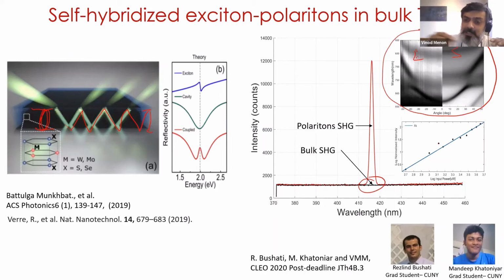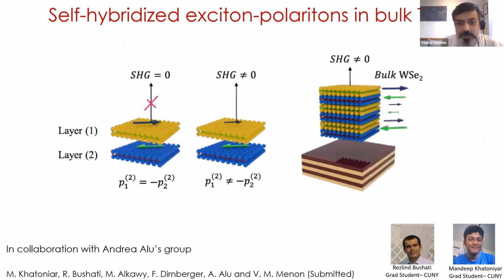And it shows the typical quadratic dependence on power. This work was led by these two graduate students, Mandeep and Rezlind, and it was last year's CLEO. It was a post-deadline paper. So we went to our theory friends, Andrea Alu's group, and we tried to understand what's going on here. And as it turns out, it can nicely come out from your electromagnetic modeling, where you see that when you are in the strong coupling regime, each of the layers sees a slightly different